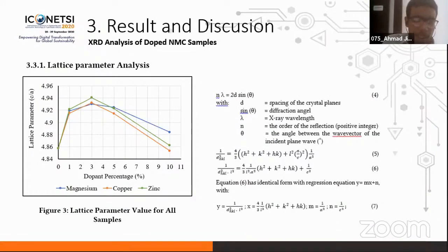This is for the lattice parameter analysis. The C per A value of the lattice parameter is a direct measurement of the deviation of the lattice from the perfect cubic close-packed lattice. Since the ideal cubic close-packed lattice has a C per A value of 4.899, a greater C per A ratio indicates a more ordered layered structure and easier transfer of lithium ions. From this figure, we can conclude that not all of the samples have a C per A value of more than 4.899. After the doping process, the NMC shows changes in C per A values. As we can see in the figure, the C per A can change depending on dopant composition and type.